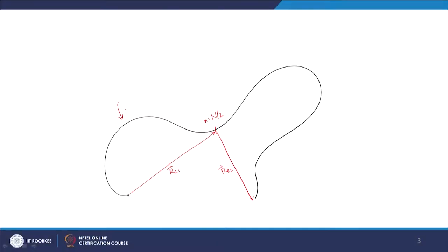Just like x1 characterized the time correlation of the end-to-end distance for the entire polymer chain, if I divide the chain into two halves, then these individual chains do have a local motion, and the local motion of the two halves is given by x2(t), the second Rouse mode.